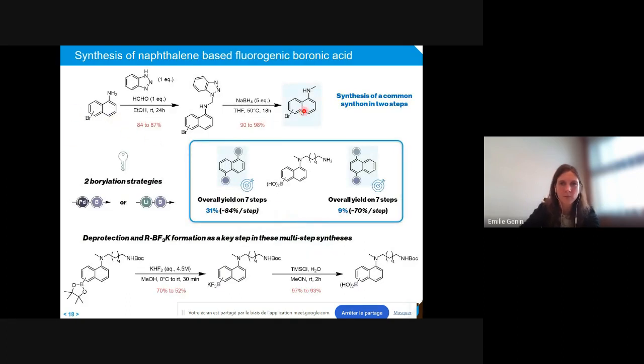Regarding the other family with the naphthalene derivative, we were also able to implement different synthetic routes to provide the targeted molecules in 7 steps with a good yield on the overall synthetic route - more than 70% per step, and even more than 80% per step with this system with a substituent on each aromatic ring.